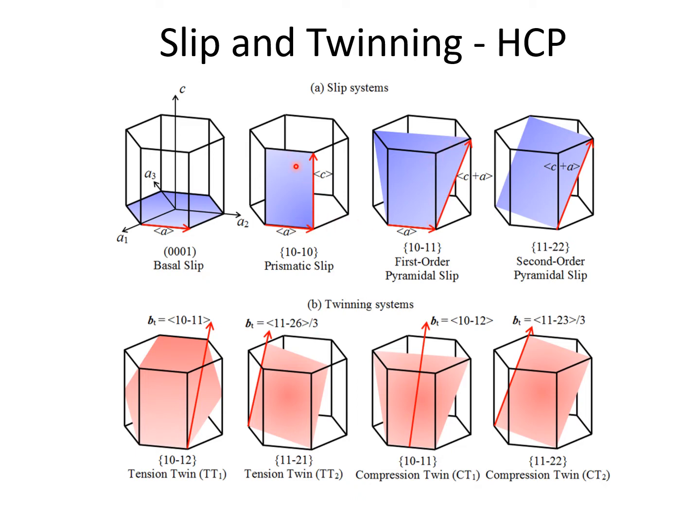But you can have slip on the prism plane in an A direction, or slip on the basal plane in an A direction. In zirconium, this is more prevalent. In magnesium, this is more prevalent. And I think I illustrate this in the ball models. The ball models are more applicable to the perfect stacking of spheres, which is closer to magnesium than anything else.